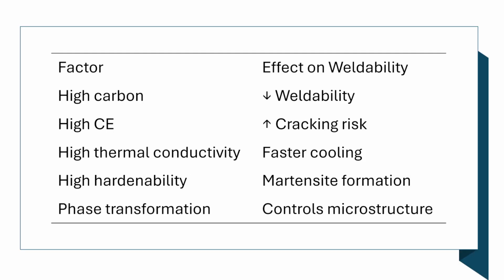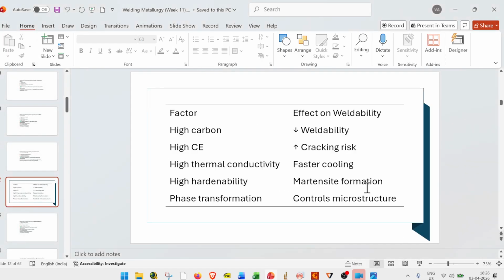So here are the few key takeaways from the first lecture. First factor, if the carbon content is increasing, the weldability reduces. If the carbon equivalent is increasing, the cracking risk will increase. Weldability reduces and cracking risk will increase. Higher thermal conductivity means faster cooling. Higher hardenability results in martensite formation, and phase transformation controls microstructure.